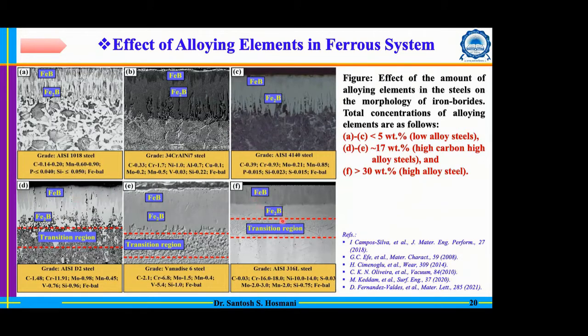Now, interestingly, as you go to figure F, which has a very high concentration, you can see the different layers there. You can see the transition zone layer. You can clearly see the FeB layer, which is darker in nature. Then you can see the Fe2B layer, which is slightly whitish in nature.